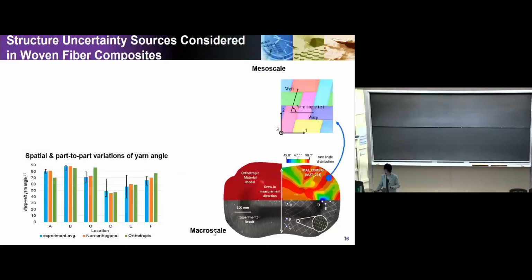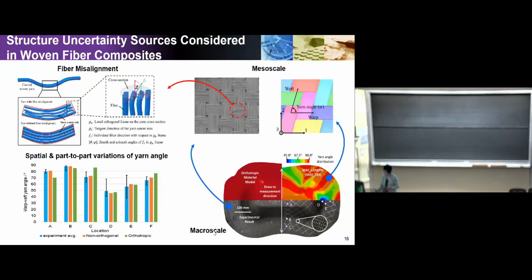So the kind of uncertainty I'm showing next involves this double dome structure after preforming. You can see the angles are different. This is the yarn angle, which differs at different locations due to the manufacturing process. Here is an example of fiber misalignment. You can see that the fiber deviates from its ideal location and it leads to misalignment that will introduce a possibility of damaging behavior. And this misalignment is described by two different angles, theta and phi, with reference to the ideal location. So this is the deviation. The angle shows how much it deviates. You can think of those as random variables, like theta, phi, as well as alpha. Those are the random variables in our problem, but they have coupling between them, okay?